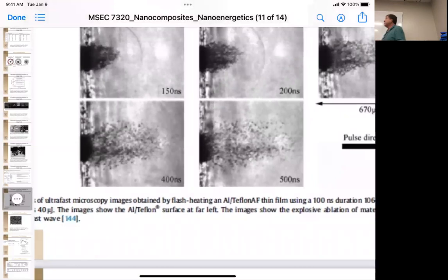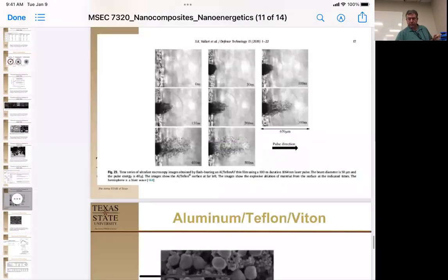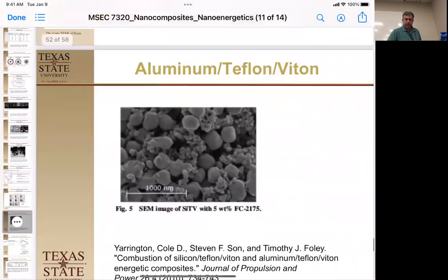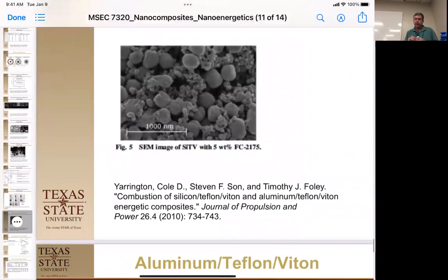So the three things that this tells us: number one, it's a very fast reaction. It can be initiated with aluminum, with a laser. And because it generated a pressure wave, it is a detonation. It does count as an energetic material. And then you can do that same thing with Nano Teflon.